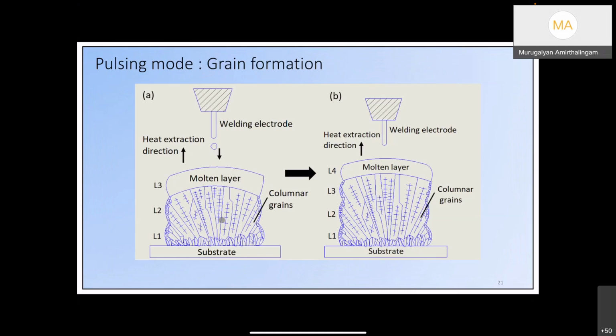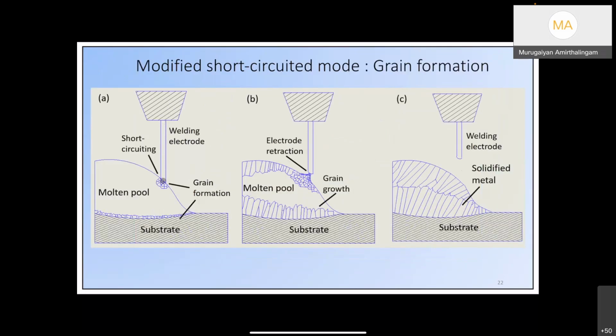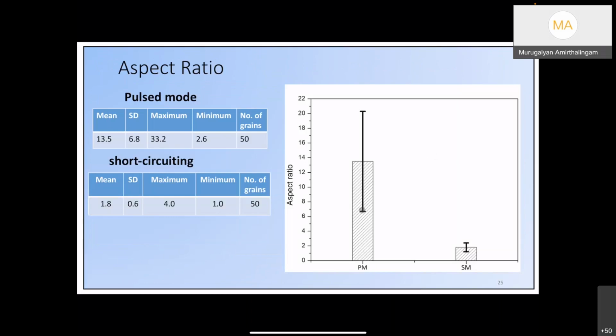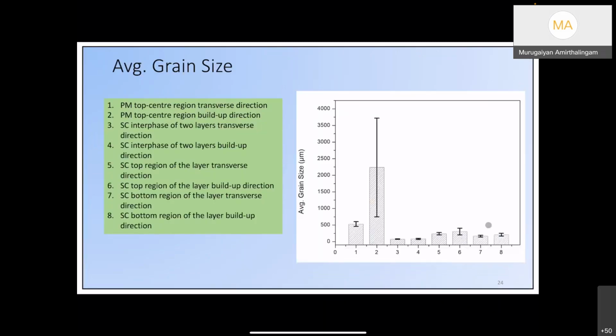And what happens in a conventional way? As I said, because of the steeper temperature gradient prevailing along the heat extraction direction, the grains grow in a planar way. When we have short circuiting, or a change in the current-voltage waveform with the metal transfer, we have a shallow temperature gradient to begin with, and also during the dipping event we change the nucleation, so the grains become much finer, and we also break the growth of grains along the heat extraction direction. So certainly the grain aspect ratio, the equiaxed nature of the grain, changes in a pulsed mode compared to a short circuiting mode. And we also get a much finer microstructure in the second case, because we understood how the microstructure evolves, and then we controlled the mechanisms so that we can engineer the microstructure, isn't it?